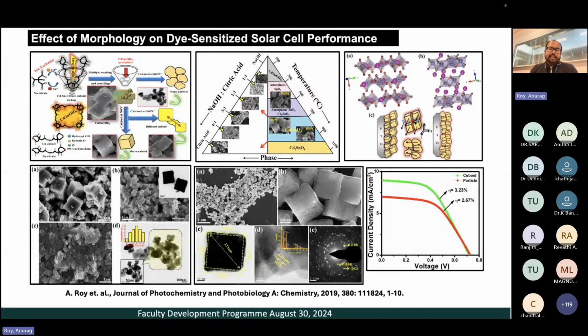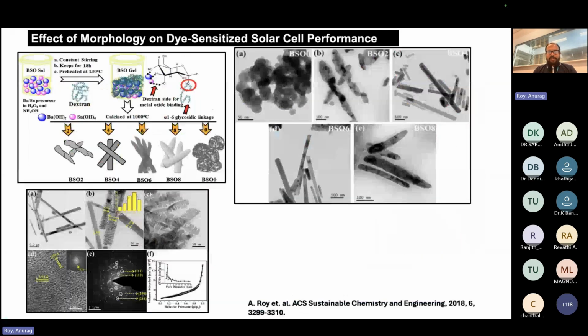Another one is the dye sensitized solar cells. So instead of perovskite, you can use a natural dye or a synthetic dye. And here I want to show you some effect of morphology, how important nanomaterials are. One is cubic, one is particle. If you change your morphology and the shape of your particle, that can make a direct impact on the electrical performance.